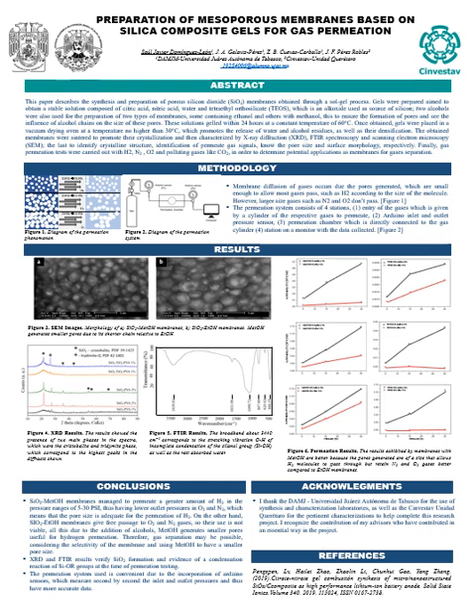The permeability coefficients were determined by establishing a correlation between the highest and lowest pressures observed for each membrane, corresponding to the gas that underwent permeation. This correlation was then multiplied by the thickness of the membranes, which in this instance remained constant at 180 micrometers. In Figure 3, the scanning electron microscope micrograph showcases the morphology of each fabricated membrane.